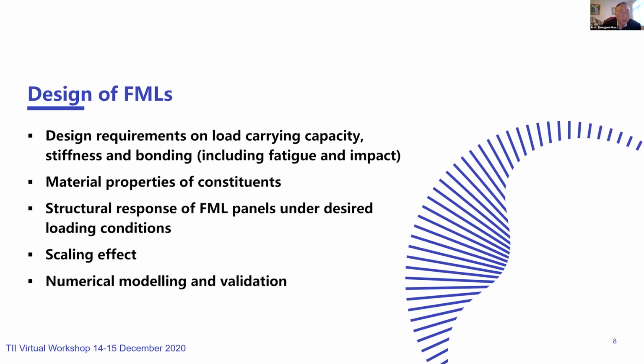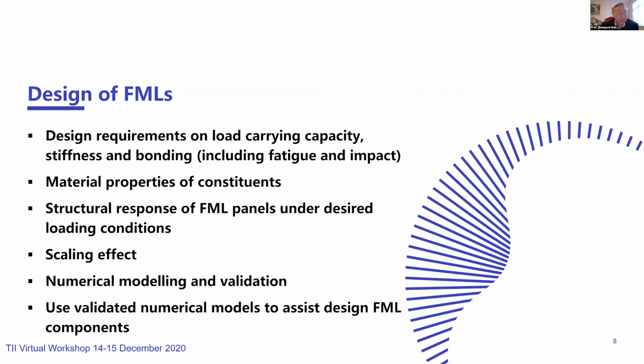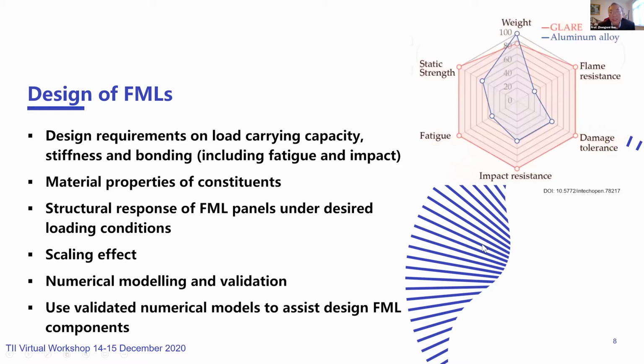Numerical modeling and validation are quite important. Nowadays, we have very powerful computers, so we can make use of this power to do a lot of parametric studies to help design. So I talk about using validated models to assist the design of fiber metal laminates. This drawing shows GLARE, the fiber metal laminate, in red, and just aluminium alloys in blue. GLARE has lower weight, but also better static strength, fatigue, impact resistance, damage tolerance, and flame resistance. They're much better than pure aluminium.